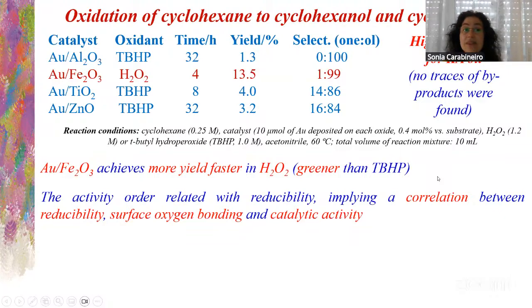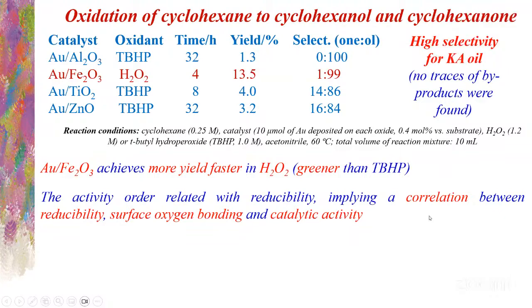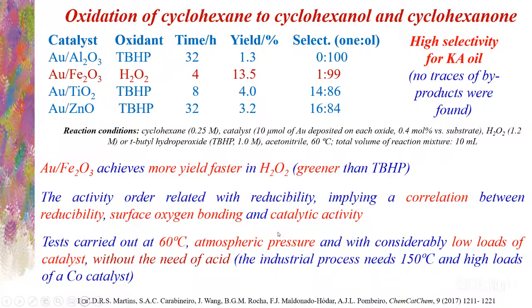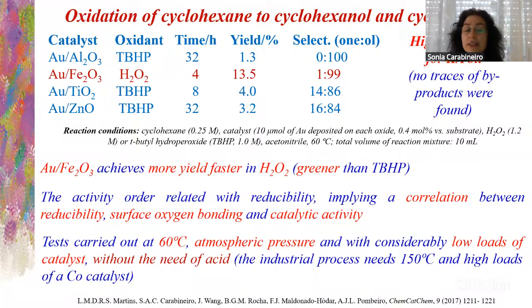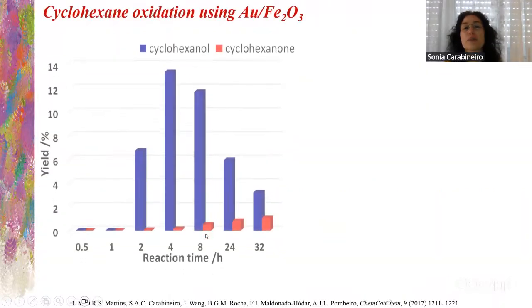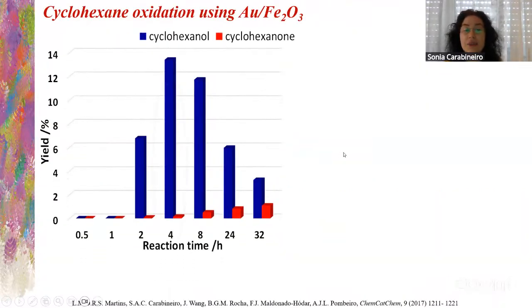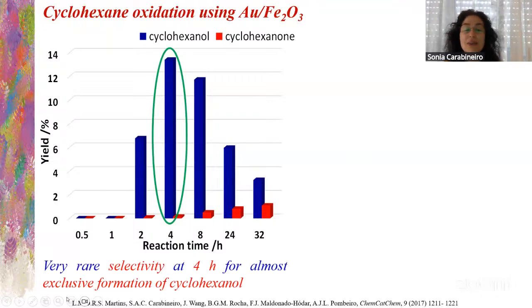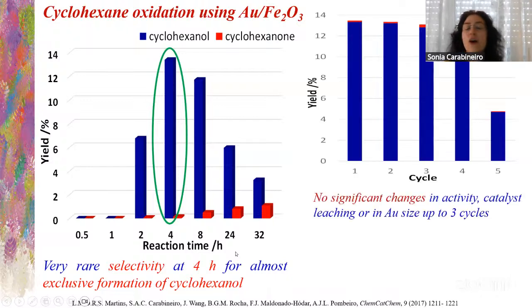So again, the activity is related with reducibility. It implies a correlation between reducibility, surface oxygen, and catalytic activity. These tests were carried out at 60 degrees. Remember, the industrial process needs 150 degrees and high loads of catalyst. This was with low load of catalyst and without the need of acid, which is quite good. So here, using iron oxide, we saw something interesting, which was a very rare selectivity for cyclohexanol formation. Usually a mixture is obtained.